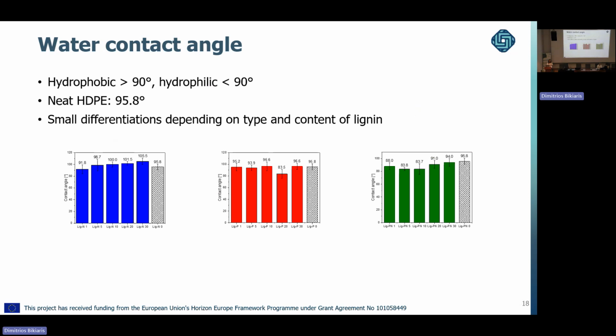Lignin is a hydrophilic compound, so we studied water contact angle to evaluate the hydrophobicity or hydrophilicity of the materials. Neat HDPE is hydrophobic with a contact angle of almost 96 degrees. Based on the type and content of lignin, we have small differentiations. Overall, the composites which have been obtained with nitrogen-modified lignin remain hydrophobic, while the ones with phosphorylated lignin and the lignin with phosphorus and nitrogen have a mild hydrophilic behavior.